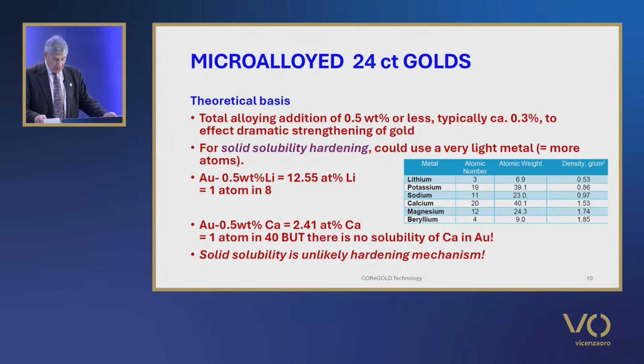Significant solid solution hardening by such small weight additions is only possible if the alloying metal is very light. That is, it has a low density and has a very small atom size compared to gold. If we examine the periodic table, the light metals that might possibly be microalloying additions are, in order of density: lithium, potassium, sodium, calcium, magnesium and beryllium, as we can see in the table on the screen.